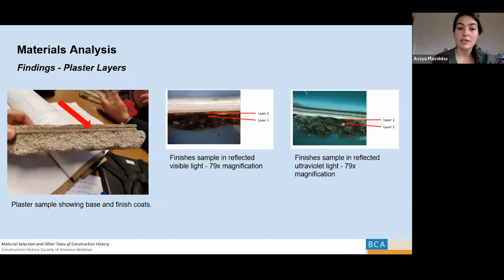The other curiosity that we found during our analysis was that within the finish coat layer, the finish coat actually subdivided into two separate layers. And you can see in the left photograph, even to the naked eye, this could be visible, where the red arrow points, you'll see sort of a line. Now you may remember Alex mentioning that there was a pause in work before they completed the finishing of the church. And we believe that this pause contributed to what we're seeing in the separation.